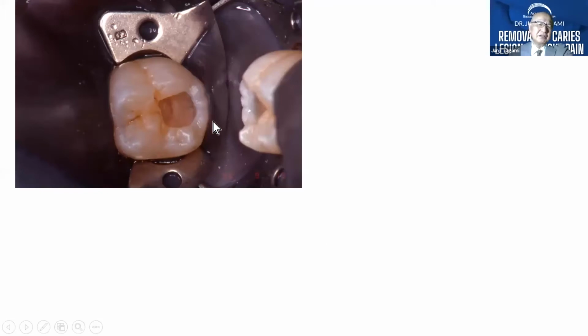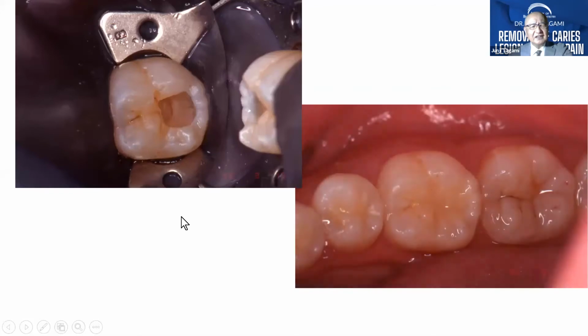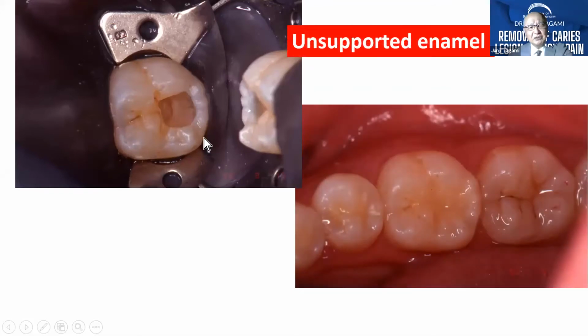So we can go back to this clinical case, and another issue we have to be concerned about is the unsupported enamel. According to the fundamentals of cavity preparation established by Dr. G.V. Black, we had to remove this unsupported enamel. But in the case of this kind of adhesive restoration, we can support this unsupported enamel by strong bonding from inside of the cavity. So we can move on to the direct composite restoration.